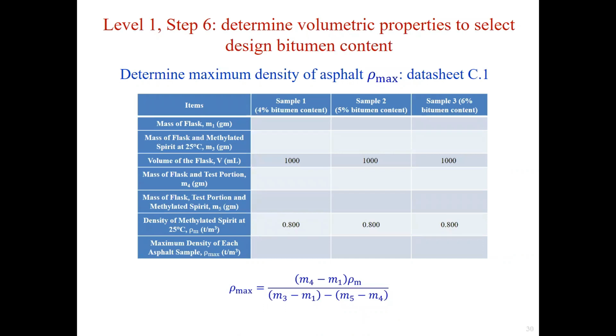After you conduct the lab testing, you should be able to obtain the measured values for datasheet C.1 and D.1. The maximum density of asphalt, or rho max, could be obtained by combining the table and the formula below, where M1 to M5 are the testing measurements.